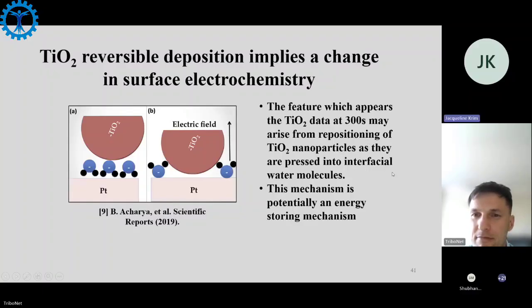It's a reversible deposition, completely reversible, which is good if you're interested in energy storage. Possibly good if you're interested in friction, which I'll get back to. But it's important to know that that totally changed the interfacial properties simply by going slow enough, applying that field for 300 seconds. Okay, next slide.